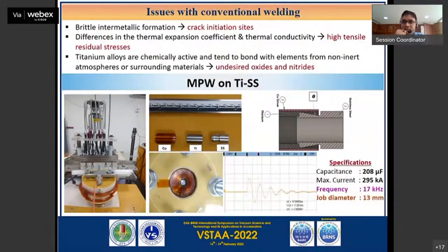Usually when we apply conventional welding techniques to titanium and SS joints, there are certain challenges. There is brittle intermetallic formation. Also, titanium and SS have different thermal expansion and thermal conductivity, so they react to temperatures in a different pattern. So when the bond is made with conventional techniques, ultimately failures are seen at the joints. Also titanium alloys are quite chemically active. When we try to weld them with conventional techniques in a non-inert atmosphere, oxides and nitrides form. So usually the weld part in conventional techniques is a failure part.